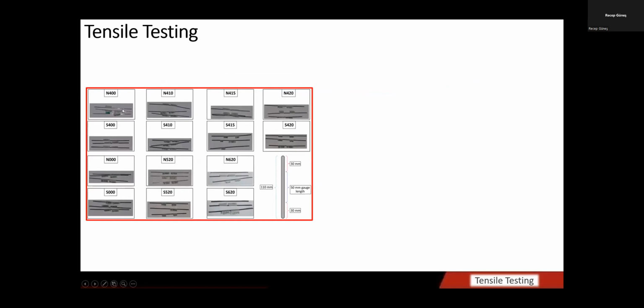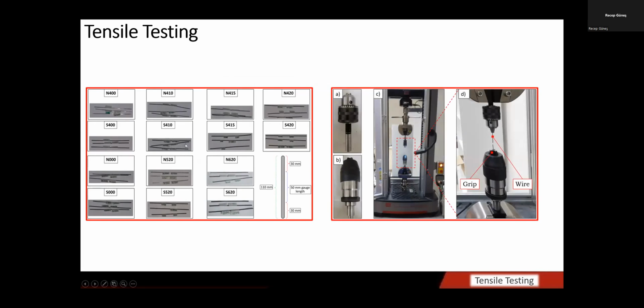Next is tensile testing of all the compositions and structural configurations which I have shown. Because the wires are 1 millimeter in diameter, it is very difficult to conduct a tensile test on such wires. You must have a comprehensive gripping system which can grip the wire, not strong enough to crush it at the grip level, but not weak enough to release it or let it slip, and without transferring the stresses to the gauge length.